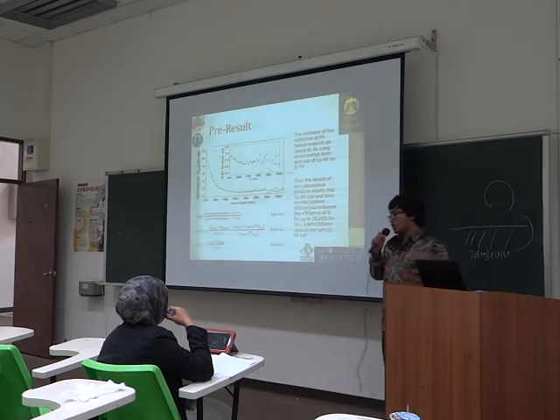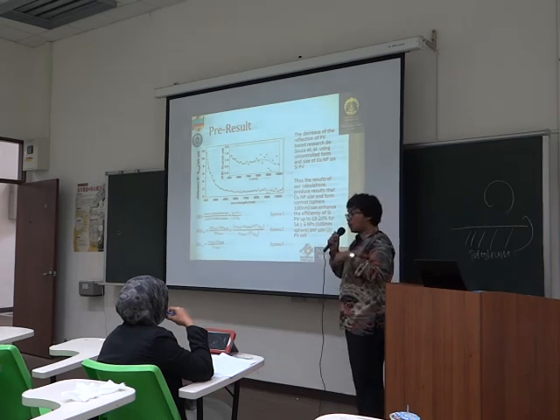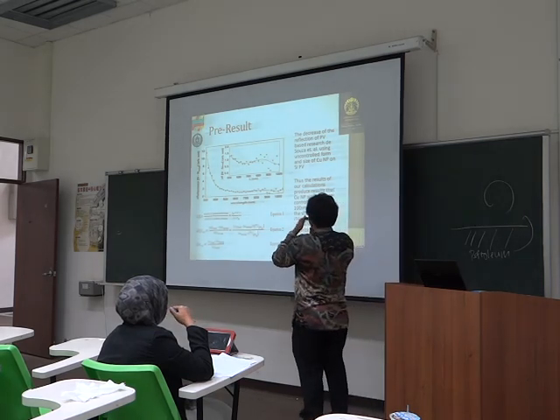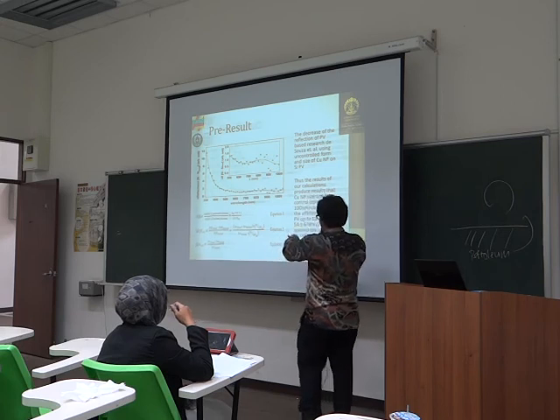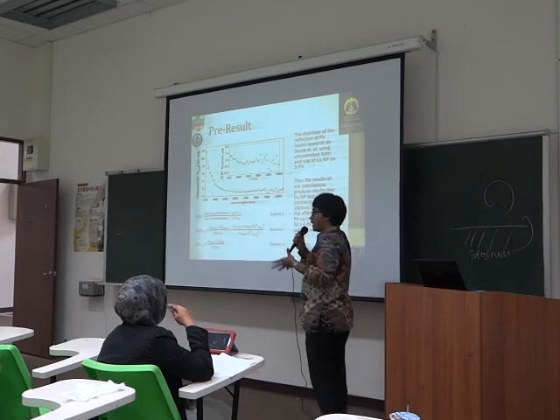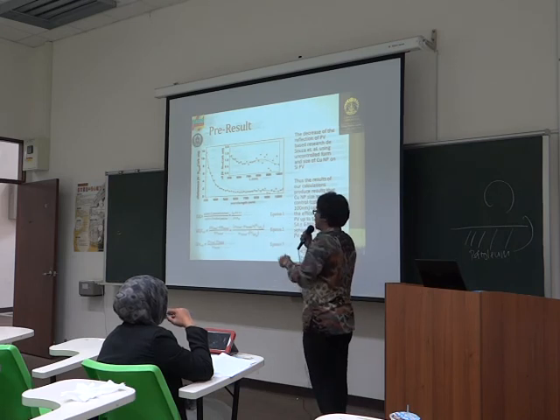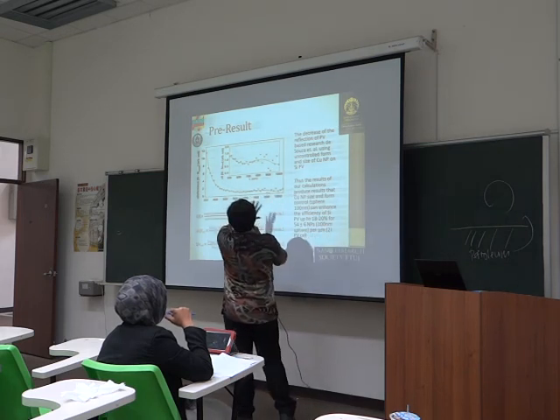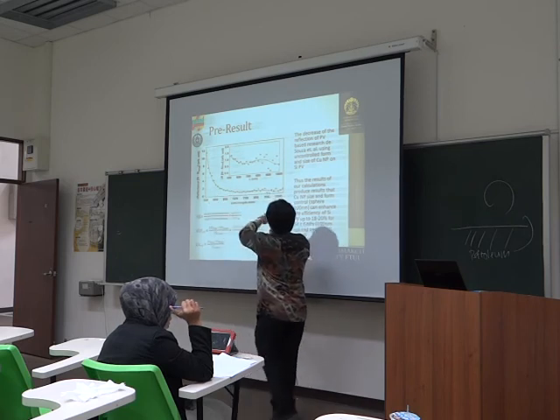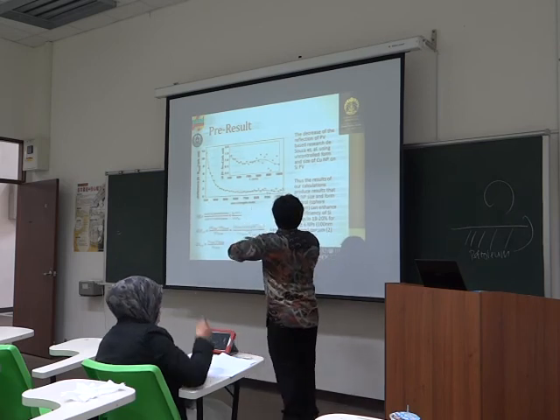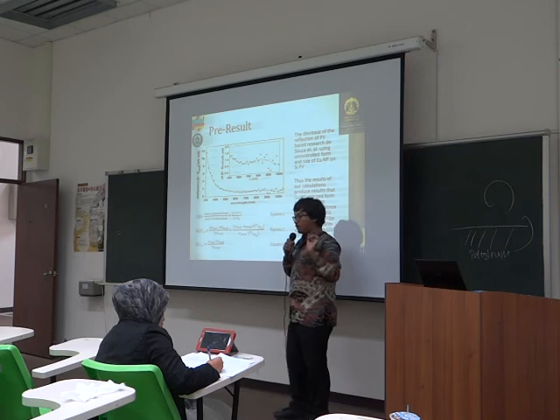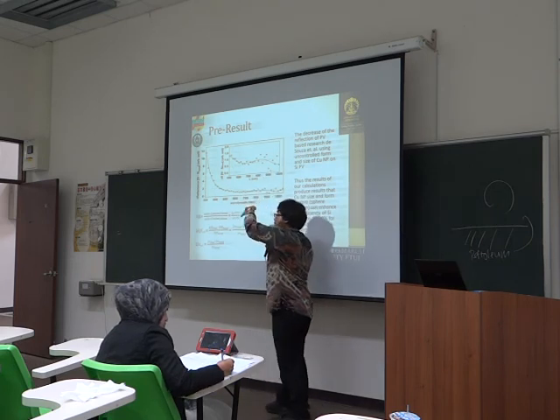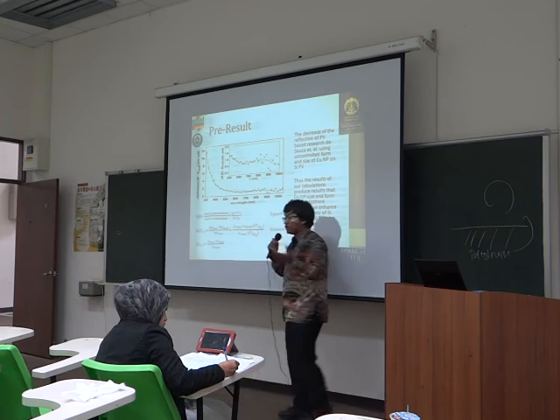This is the result. I say pre-result because it's still work in progress. But the thing that we can see here, we use the three equations here to calculate how the copper nanoparticle contributes to the increase of the surface plasmon resonance effect. We see that the reflectance across the wavelengths provided by the sun is very small. I didn't put the before chart, but before it was higher. So by using the copper nanoparticle, it decreases the reflectance, and of course it will increase the efficiency itself.